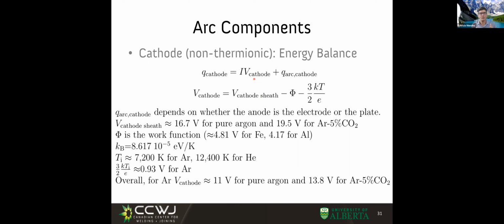The non-thermionic cathode is not very well understood. So people assume some kind of empirical cathode sheath, which we have measured too in our lab. And this ends up resulting in an overall voltage at the cathode of, say, 13.8 volts for argon-CO2 in MIG, or 11 volts for pure argon, which would be the case of TIG. Let's think of this. The anode had a voltage fall of the order of 4.5 volts.